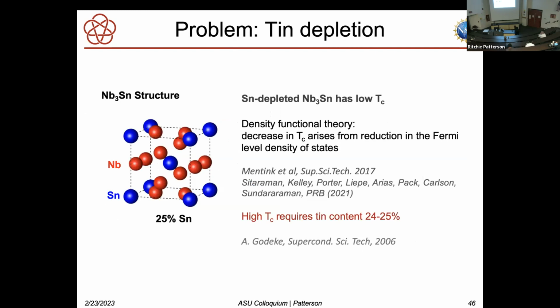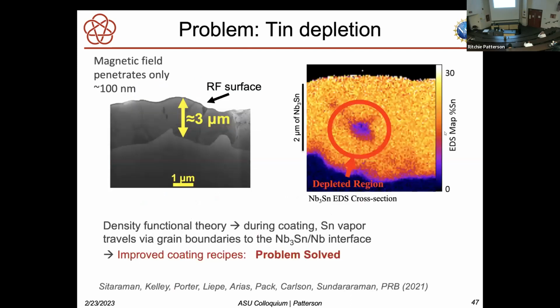You want 25% tin, but very often niobium substitutes for one of the tin atoms. And that doesn't have to happen very often to totally blow the performance. And we've done lots of density functional theory calculations to understand this effect. Bottom line is that you need 24 to 25% tin to get the performance.